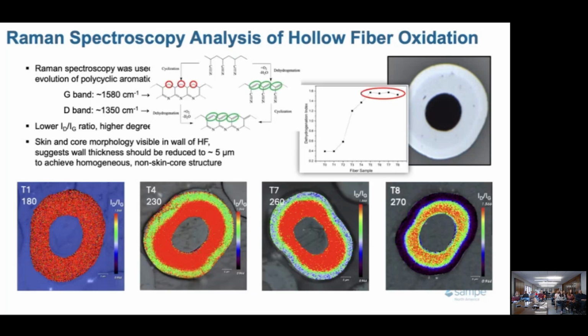It's these aliphatic hydrogens, this aliphatic bonding I've circled in red, as opposed to the conjugated bonding after the material is dehydrogenated in the presence of oxygen, that we believe underpins these results. It's as if the oxidized layer is a barrier for oxygen to go through, which we see in all kinds of materials, right? Cut an apple, look at an avocado or a piece of steel or aluminum, everything has these oxide layers.